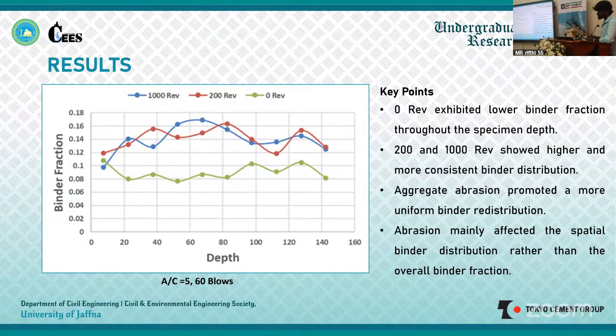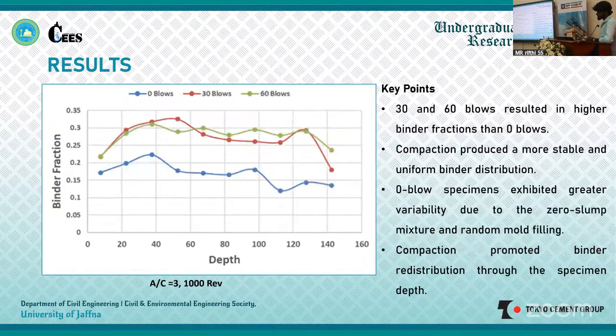And this figure shows the effect of compaction on binder distribution at an aggregate to cement ratio of 3 and an aggregate abrasion level of 1000 revolutions. The blue line represents the specimen without compaction, while the red and green represent 30 and 60 blows. The specimens compacted with 30 and 60 blows show higher and more stable binder distribution compared with the specimen without compaction. The specimen without compaction shows larger variation because the concrete had a zero slump mix.